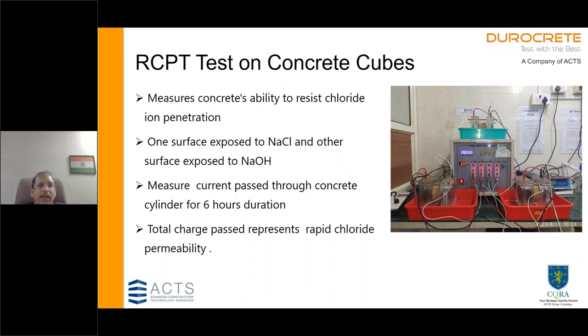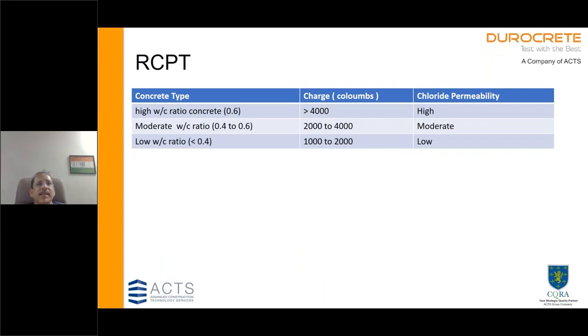There's a NaCl solution at one end, you allow the chloride ions to penetrate, and we measure the current passed in a 6 hour duration. The more charge that passes through the concrete, the more chloride penetration inside the concrete. Standards say that if the charge is more than 4,000 coulombs, the chloride permeability is considered very high; 2,000 to 4,000 is moderate, and 1,000 to 2,000 is considered low.